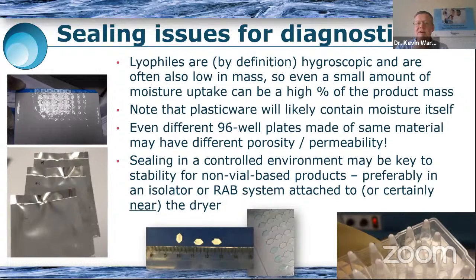And what we've found, particularly in some of the diagnostics we've worked with over the years, is that we've had to be very careful about the packaging. If we've got a successfully freeze-dried material, it's probably quite hygroscopic. But of course, if they're very low mass, then that means that even a small amount of water going into the product over time could represent a very high percentage of the product mass. So immediately after freeze drying, we might have 2% moisture, but over a period of months, we might find that suddenly that goes up to 10%.